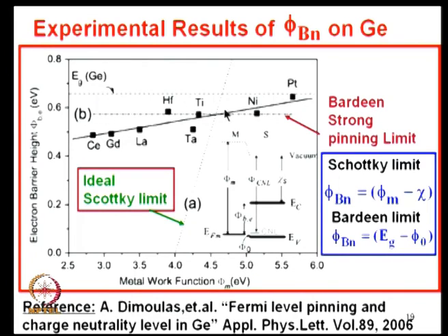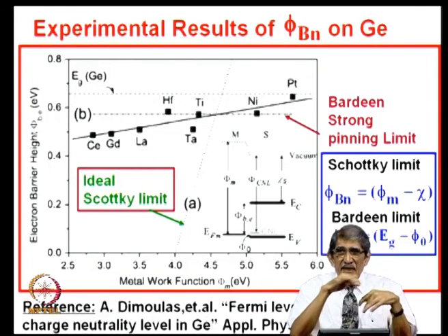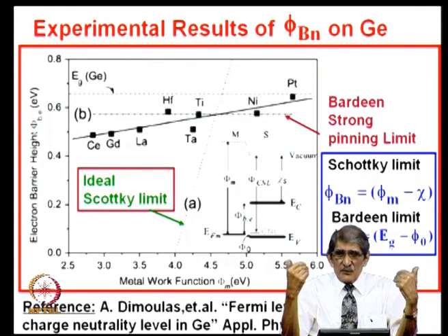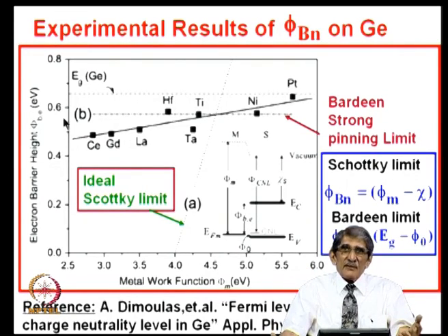I can draw a straight line like this, saying it is almost flat compared to when I am using hafnium, titanium, nickel, etcetera. It is almost flat, close to about slightly less than 0.6 electron volts. Remember, the band gap of germanium is 0.66 electron volts. In the case of silicon, we had 1.1 electron volts and you had the barrier height flat coming to about 0.8 electron volts. That is about 2/3 of that. In the case of germanium, band gap is 0.66 electron volts. So, what you get is slightly less than 0.6 electron volts, that is below 0.6 electron volts.